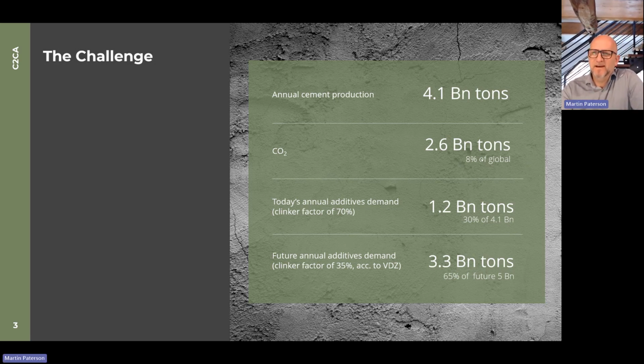A lot of the improvements in the industry have already been started. The industry is working since many years on improving efficiency of the plants, on implementing alternative fuels. For me, one of the biggest levers is the reduction of the clinker factor, and the clinker factor currently globally is at around 70%. Actually, it was lower already, but it increased again. And the reason for that is scarcity of the current additives, mainly being slag and fly ash.